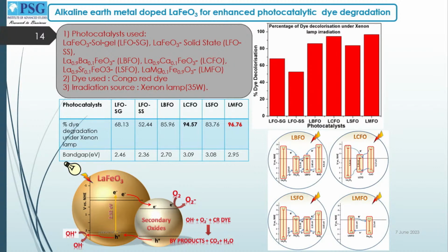Now, under perovskite materials, we worked on lanthanum ferrite to improve the photocatalytic activity. We tried to dope divalent alkaline earth elements in the position of lanthanum, and then, with the experience of the efficiency of magnesium, we also tried to dope magnesium in the lanthanum position in the lanthanum ferrite perovskite, and we studied the dye degradation characteristics. Here also we found that magnesium doped lanthanum ferrite gave the highest dye degradation. We also studied the band characteristics.